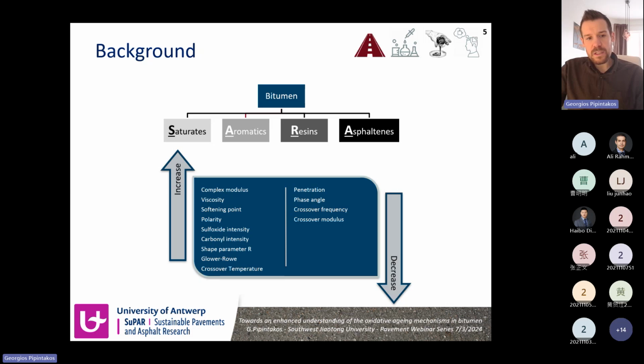Now, literature also has reported changes of mechanical and chemical properties of bitumen with aging. For example, it has been reported in the literature that with DSR, the dynamic shear rheometer, we can observe an increase of the complex shear modulus, and also with Fourier transform infrared spectrometer, or FTIR, we can see an increase of sulfoxides and carbonyl functional groups with aging.